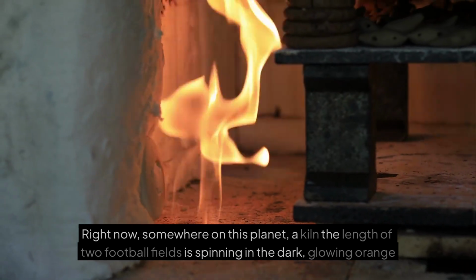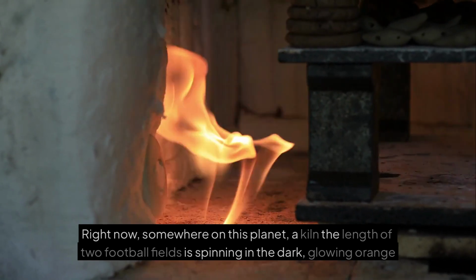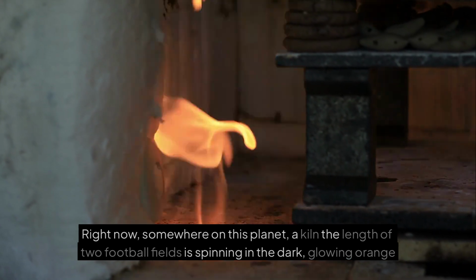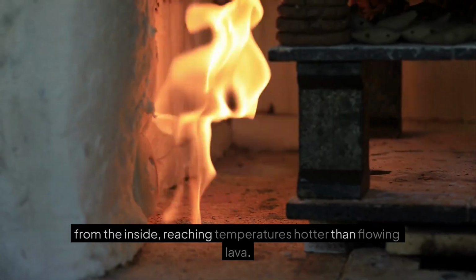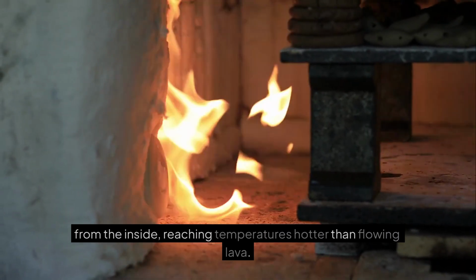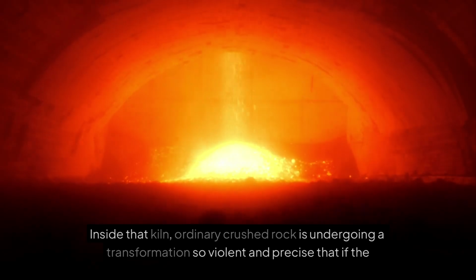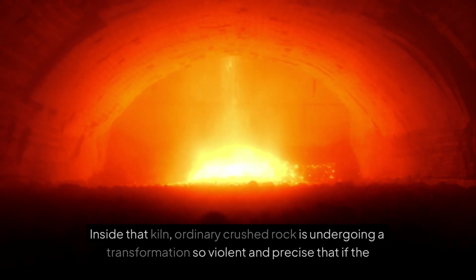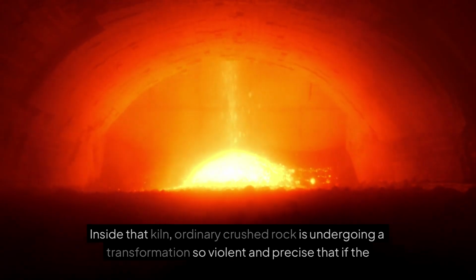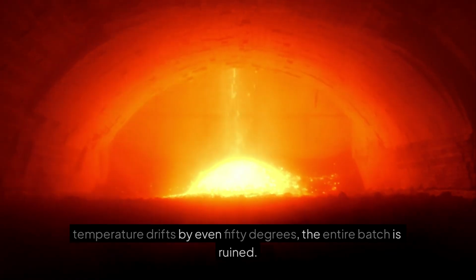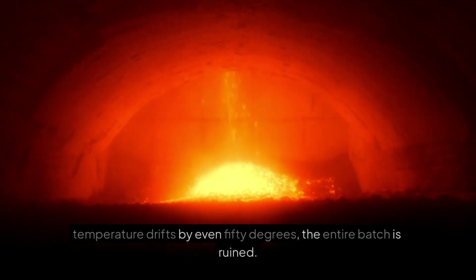Right now, somewhere on this planet, a kiln the length of 2 football fields is spinning in the dark, glowing orange from the inside, reaching temperatures hotter than flowing lava. Inside that kiln, ordinary crushed rock is undergoing a transformation so violent and precise that if the temperature drifts by even 50 degrees, the entire batch is ruined.